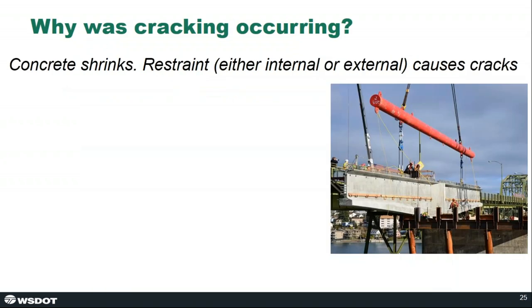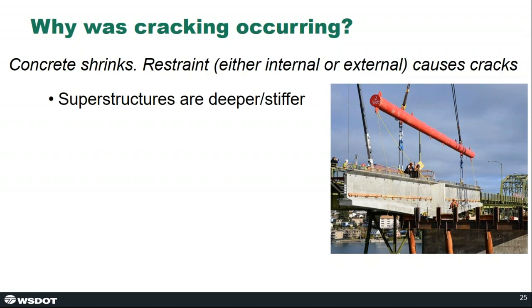So why was cracking occurring? Taking a step back, concrete shrinks, and any form of restraint, whether it's internal or external, can lead to tension cracking. And so there's a few factors at play here. One, as we push out span lengths further and further, our superstructures become deeper and stiffer. And the stiffer the supporting elements are, the more restraint they provide against the concrete as it wants to shrink during hydration.